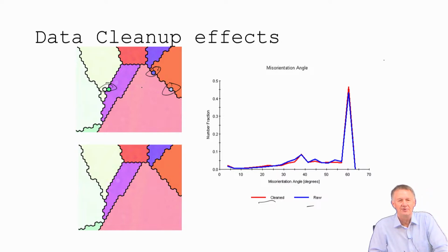And the other thing is boundary statistics, right? You want hundreds of thousands of boundaries. And so a smaller step will just take a lot longer to collect and a lot longer to analyze. So there's always a trade-off. But that would be one of the options, right? Especially if there are small grains in there, you'll see them now with smaller steps.